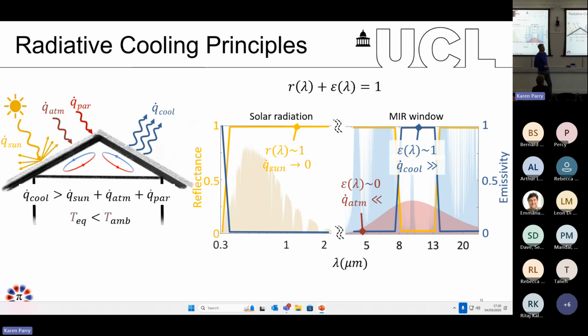At the same time, the emissivity and the reflectance of the surface are not independent quantities. They are related by this very simple relationship. The absorptivity should be 0, so the surface should not absorb anything, but it should emit very, very strongly between 8 and 13 microns. And in this way, we minimize the solar heat flux, minimize everything that comes from the surrounding atmosphere, and maximize this Q-cool component. And so to satisfy this equation. But what I have left is this parasitic heat component. And actually, this is the Achilles heel in the field. This is something that has been overlooked, but it's really essential, as I will present now.